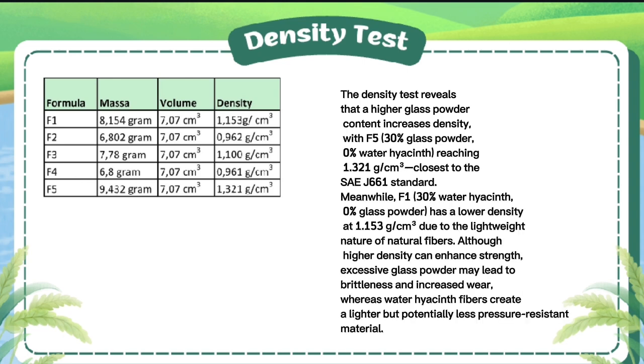Density test. The density test reveals that a higher glass powder content increases the density, with F5, which is 30% glass powder and 0% water hyacinth, reaching 1.321, closest to the SAE J661 standard. Meanwhile, F1, which is 30% water hyacinth and 0% glass powder, has a lower density at 1.153 due to the lightweight nature of the natural fiber.